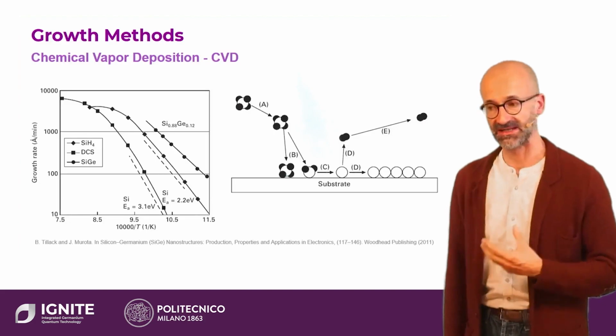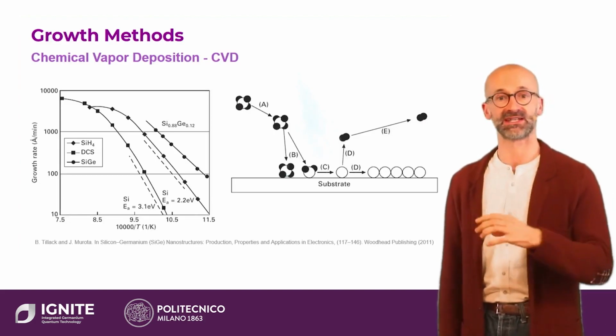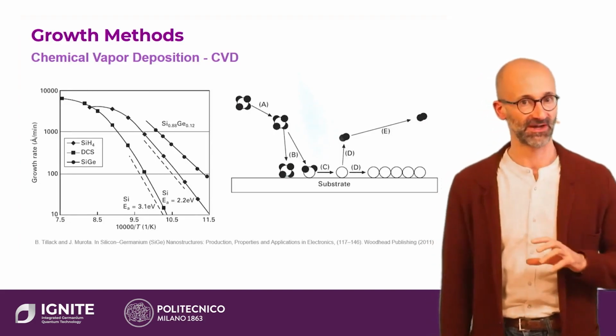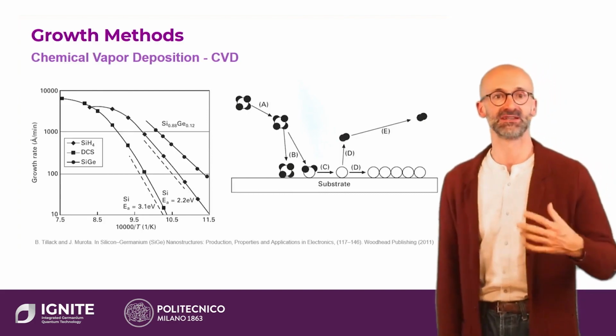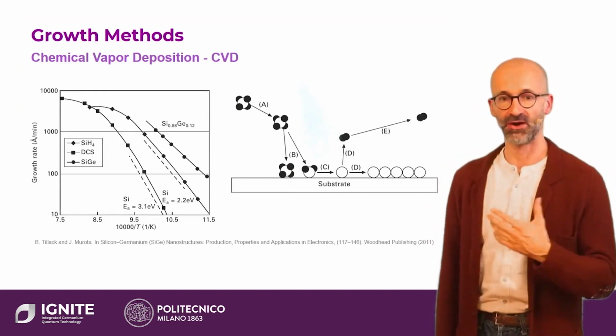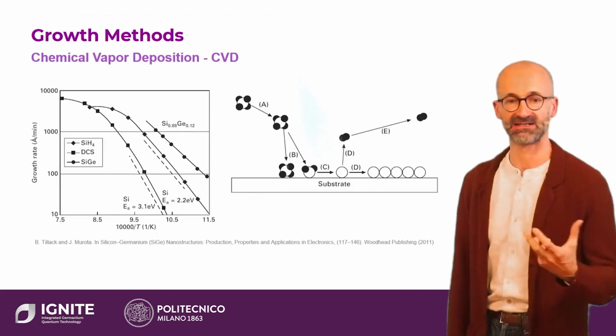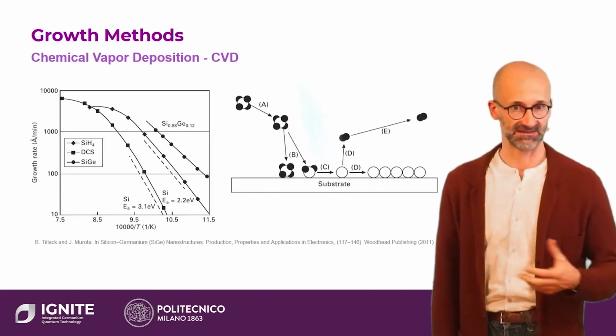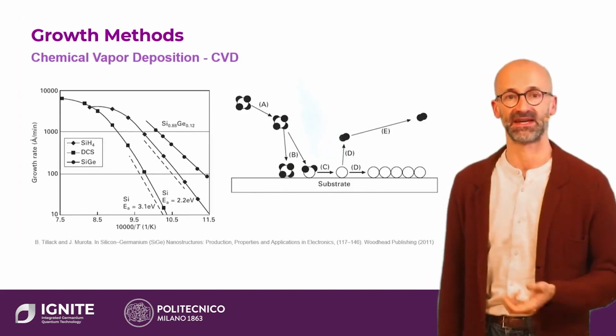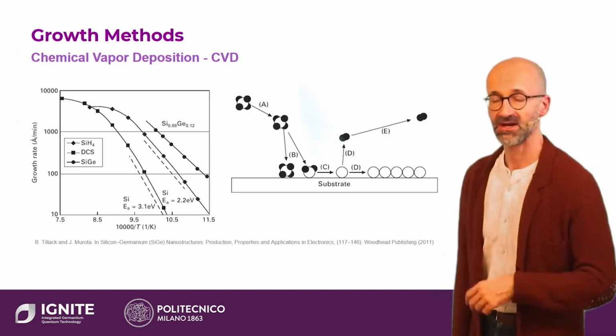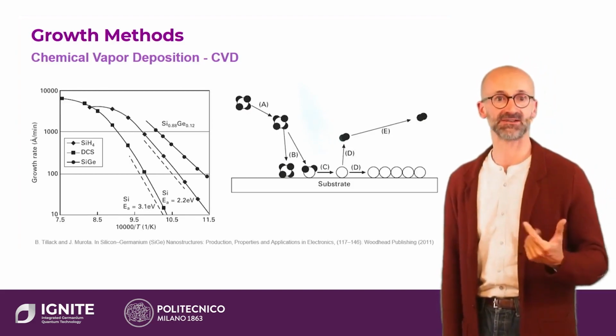The second thing that it means is that the precursor molecules only attach in chemically favorable sites. And this means that the crystal is almost perfect. There is no incentive for these precursors to attach in the wrong places. They always attach in the right places because they have to attach to the chemical bond. So very high quality material results.